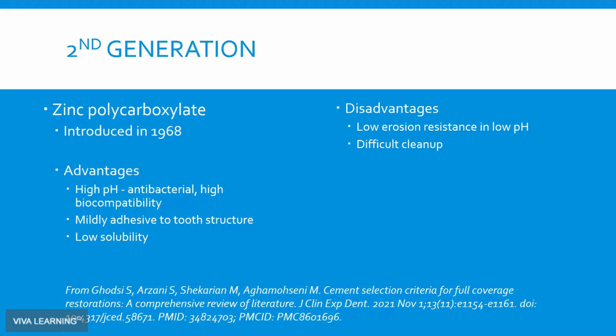But regardless, in 1968, they weren't thinking that far ahead. They were just thinking, wow, we finally have something that sticks to tooth. It's fairly low solubility and fairly high in terms of biocompatibility. The cleanup of this can be a little bit tricky, mainly because it goes through a gooey, or what I call a gummy phase, where it gets very stringy. It takes some experience to do an adequate job cleaning it up without causing problems.